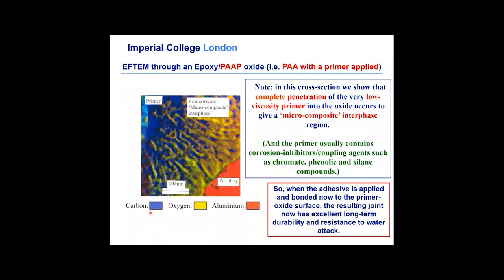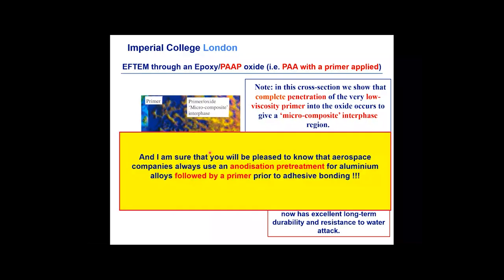So you can see now the primer, and carbon is blue, remember, the carbon penetrates deep into the oxide. So you get primer penetration into the oxide. So you actually form a micro composite interface region. No longer does the adhesive or primer just sit on the top, it actually penetrates into the structure. And when you do that, you get excellent long-term durability and excellent resistance to water attack. And I'm sure you'll all be pleased to know that aerospace companies always use anodization treatment followed by a primer before they apply the adhesive. And by this technique, they get excellent durability, and also by applying the primer on top of the freshly treated oxide, they can actually store the primer-treated oxide for some time before they have to adhesively bond it. So it's a manufacturing aid as well as an aid for durability.